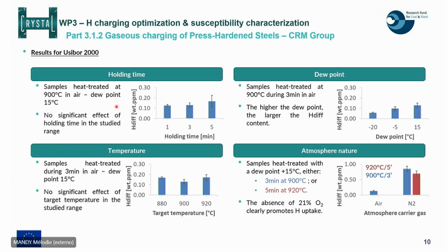So here are the results for Usibor 2000. Here we have decomposed the parameters. Firstly, on the top left, you see the effect of the holding time. We made vary the time between 1 and 5 minutes. You see that the effect is quite limited in terms of hydrogen uptake. Here you see the diffusible hydrogen content, what is called HDIF, which is always on the y-axis, as a function of the parameters that we deal with. In terms of holding time, we have quite limited effect, and it's also the case with the temperature. The temperature was really slightly varied. We are really in the process window of the steels, so we have only adapted the temperature by 20 degrees Celsius, and you see that in that studied range, we have very little impact.